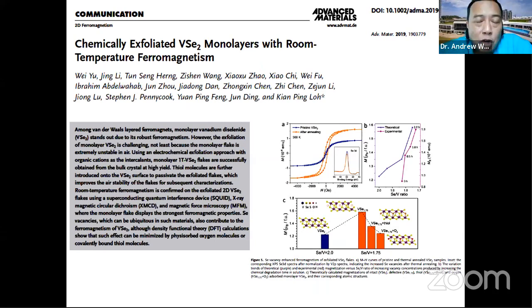However, there's another controversial result last year from our colleague's group, Lo Tianping, who's in the chemistry department. It turns out that he was working also on the same material, but by electrochemical exfoliation. So it's a chemistry method. And they showed that by chemically exfoliating this material, it is magnetic. But we must remember that this kind of exfoliation method is very dirty and there could be contaminants on it.